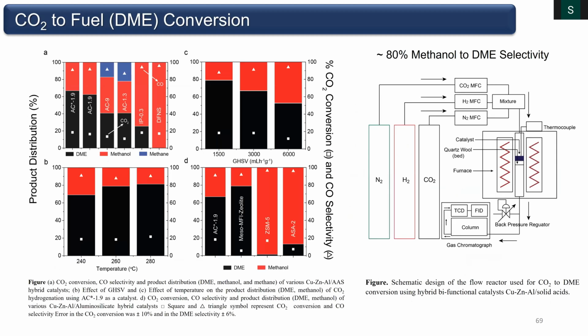We also showed the use of this for CO2 to fuel conversion, where the catalyst is copper, zinc, aluminum. But once you form the methanol, you have to convert methanol into DME. You cannot use methanol as a fuel, right? So you have to convert it into DME, which is a gas. So I don't know why people go for the methanol to DME. I feel methane is a far better solution. Anyway, if you produce the methanol, we can convert that to DME with 80% selectivity using these amorphous zeolites.